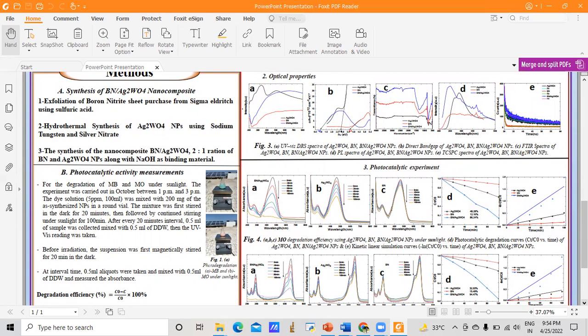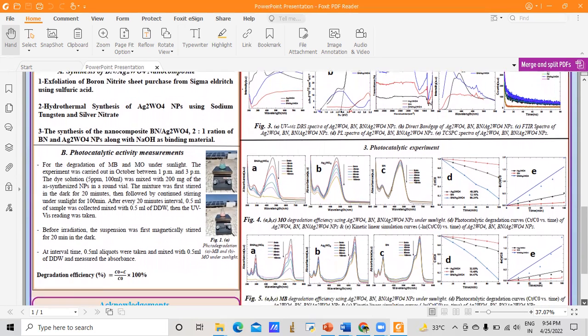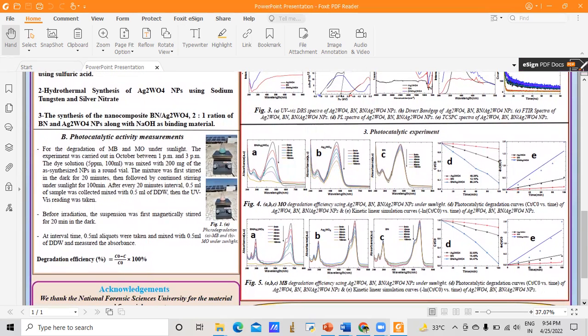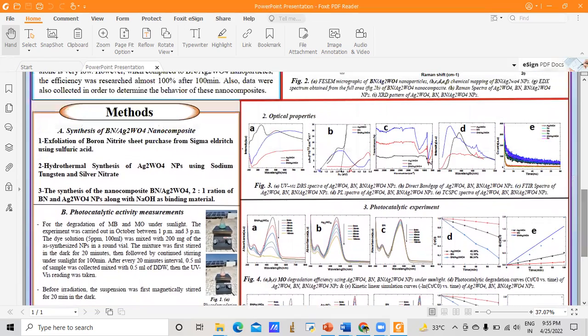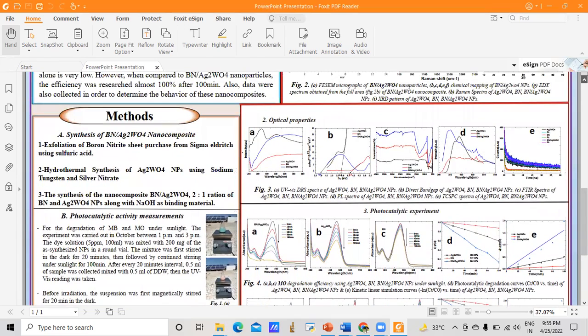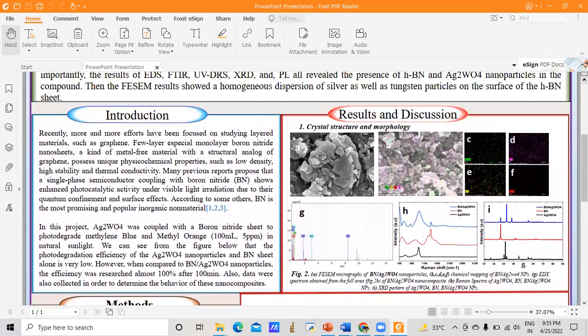absorbance was taken. So before irradiation, the suspension was first magnetically stirred for 20 minutes in the dark, and then at interval times 0.5 ml of this solution was taken and mixed with 0.5 ml double distilled water and then the absorbance was taken. So here is the degradation efficiency formula which we use to determine the efficiency of the different nanoparticles made.